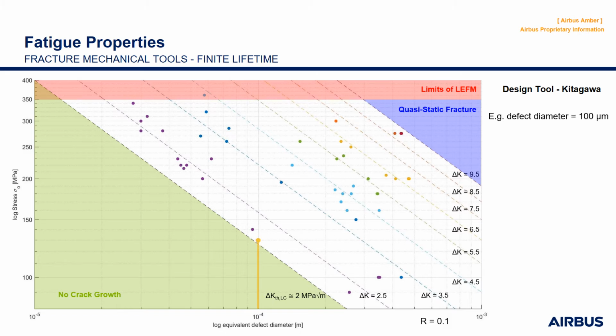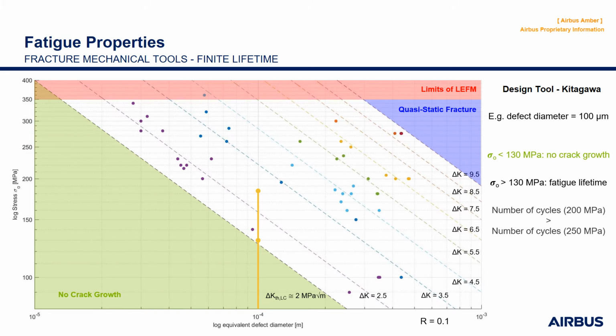If we now detect, for example, a lack of fusion with 100 micrometers, one can actually say that below this 130 megapascal, no long crack growth will occur, and the material is within its endurance limit. But crossing the border of this 130 megapascal, one will face fatigue crack growth. Even a certain dependency can be seen for the number of cycles. And with regard to upcoming certification, a constant range of defects for a certain machine material combination must be ensured.